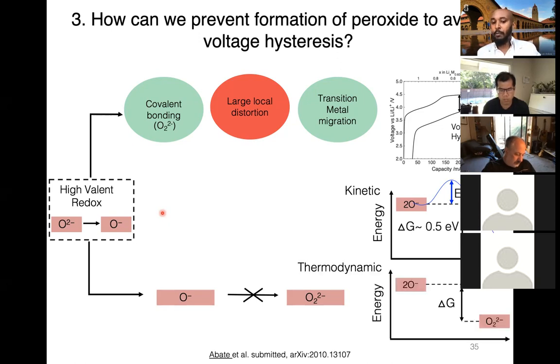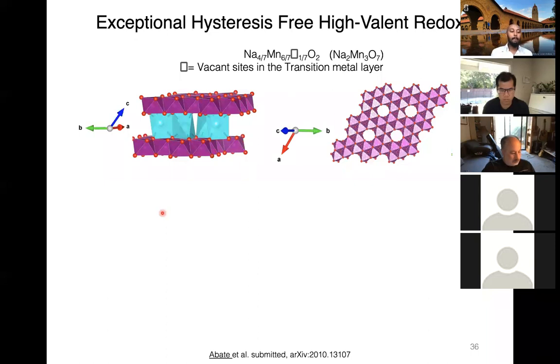Another is an approach from thermodynamics, where one can think of a material design principle where we actually reverse the stability of this oxide species. Therefore, as opposed to the peroxide being more stable, can we make the O- more stable through material discovery and material synthesis? It turns out that there is a material that behaves in a way that we can actually prevent the peroxide formation and stabilize the O- species. I will tell you which of the two mechanisms helps us understand the behavior of such a material. And this material is what we call the sodium manganese oxide, as shown over here.